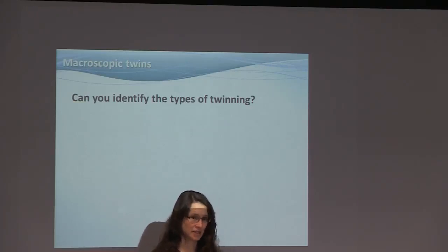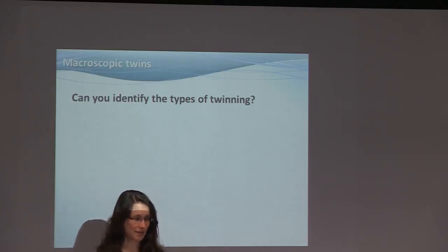Yes, that is true, although if you see splits everywhere... Sometimes you come in particular with a crystal where you think it's not twinned, and you measured it at a home source with a CCD detector, and you bring it to the synchrotron where you get much sharper spots, and suddenly you see the crystal is split. So this is common. In this case, one of the possibilities for split crystals is sometimes just to make the box bigger and not worry. It's not the cleanest way to treat it, but it's a possibility.